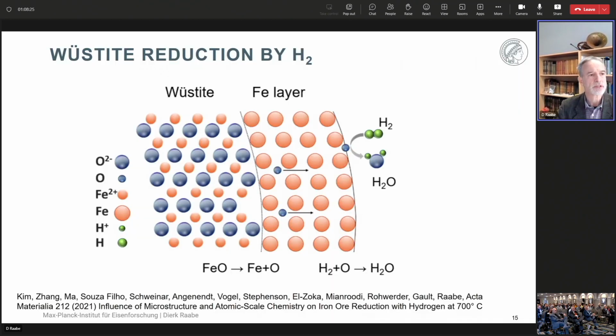So the elementary steps for this last sluggish stage of the wüstite to iron transformation are shown here. Left-hand side, the wüstite. Right-hand side, you see the iron layer. And the first reduction was, of course, at the surface, where water was formed due to the surface reduction of the wüstite by the incoming hydrogen, which must dissociate and react with the oxygen.